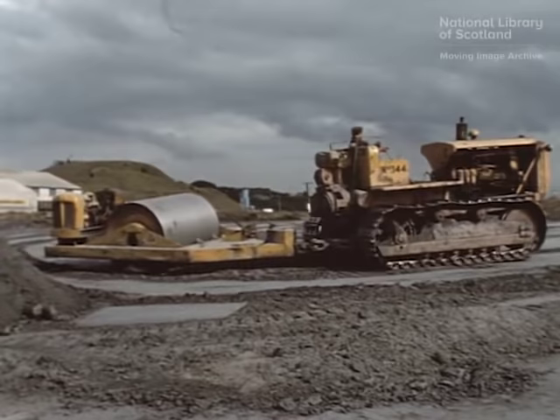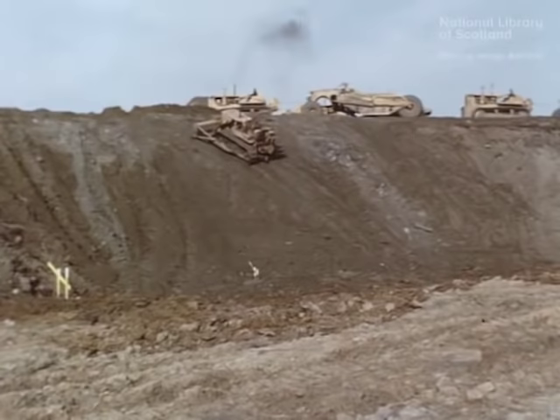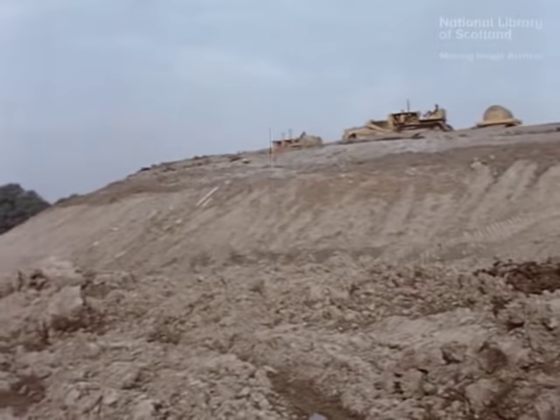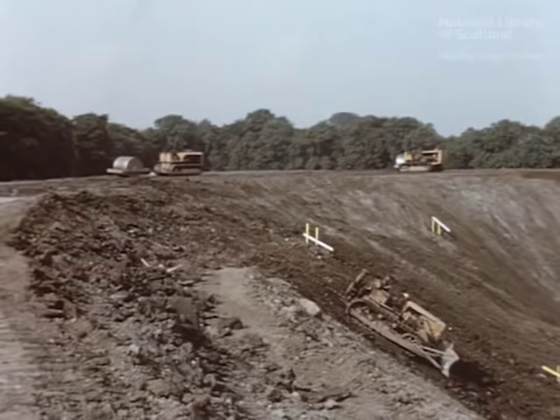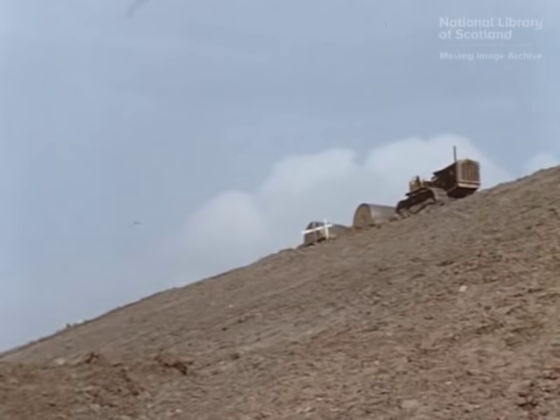This material is ideal for such situations, for being lighter than clay or blaze, it requires less support from the underlying strata. To ensure adequate compaction and structural soundness, even the highest embankments, some as high as 60 feet, were built in 12-inch thick layers, each layer being thoroughly rolled and graded before the next layer was spread. At the same time, side slopes were carefully graded and trimmed to their final shape — not always to straight geometric lines, but often to varying slopes and contoured curves, so that the completed roadway would better merge with the surrounding landscape.